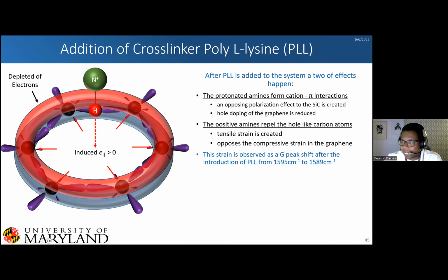And now you're thinking, so why didn't that happen as significantly in the CVD graphene case? Well, if you think of the CVD graphene case, the grain sizes are actually pretty small, right? They're on the order of 10, 20, 30, 40 microns. And so in terms of a long range pi network, you don't have it. And any strain that you generate is very local to that grain. And so once you get to the grain boundary, that strain effect is lost. This is something that doesn't happen for epitaxial graphene, because our grain sizes are on the order of millimeters, essentially across our entire sample.